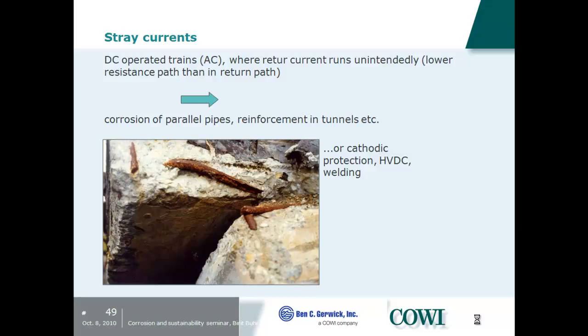The challenge is that you would like to include them where you estimate you would have corrosion in a critical amount, or where you don't expect them, meaning in different depths, but also in different levels. We have another bridge which has been monitored also with the POST system, and it was clear from that that we had a higher corrosion rate just above the tidal zone, even though the chloride concentration was lower.